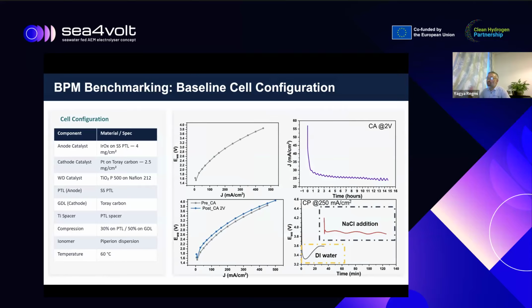So what we have done beyond what I call the state of the art in seawater electrolyzers is that we started looking at each and every component in the bipolar membrane electrolyzer, starting with the water dissociation catalyst. The baseline where almost everyone starts is titanium dioxide. We looked at different types of titanium dioxide, anodized, rutile, brookite, and different loading of TiO2 onto the water dissociation catalyst layer.